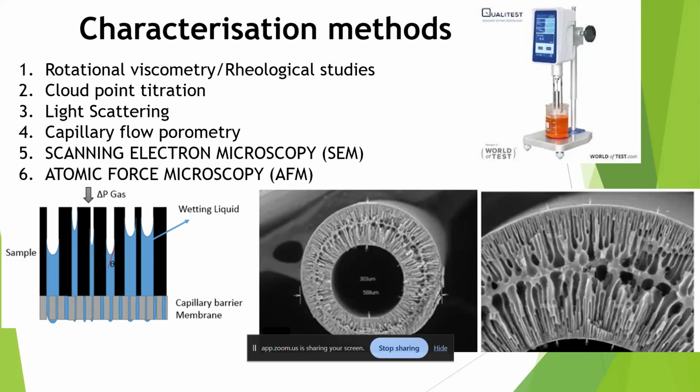Another one is the cloud point titration. As I have mentioned, it is a simple titration that is very commonly practiced, just by taking a sample of the dissolved polymer solution and adding drops of water, and we get to see at what point the color changes.